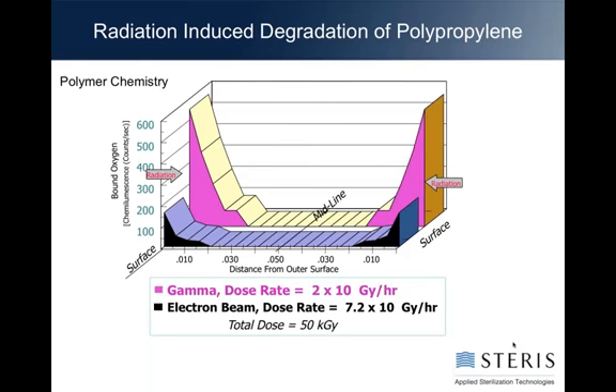As a result, it is possible to see some of the changes in a product when they are oxygen driven be different in total amounts of change when you look at a very rapid dose rate, for example, that an E-beam unit can produce versus what a gamma unit can produce. And this picture shows where you've got a deeper penetration of the oxygen on the product when it's gammaed versus the one that's E-beamed for the same dose. And that's because the electron beam is depositing in a very narrow, discrete path a lot of ionization events very, very quickly, and then it's turned off. So one of the key features to have that change occur, which is that the oxygen and the ionization be going on at the same time, is stopped.